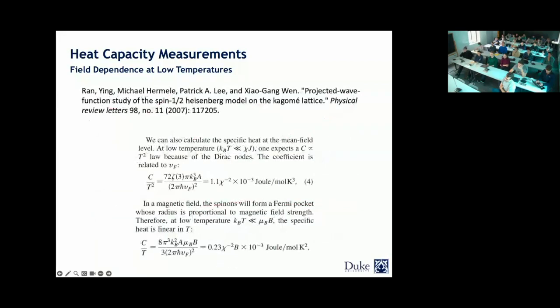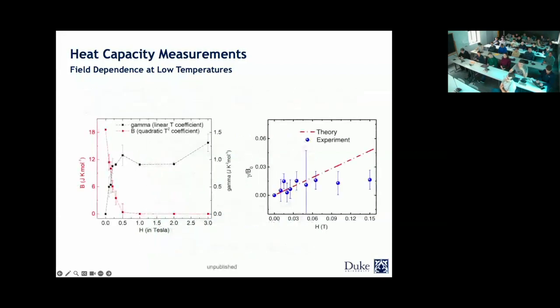Okay, so let me bring you back again in here. The reason for that is that not only would you be able to look at the behavior of the specific heat at two different ranges, zero field and finite field, but if you take the ratio of these two, it actually gives us the value that you would expect to see for different fields. So we did that. We started to look at the different values for gamma and B. The gamma would be the linear T coefficient, and B would be the quadratic coefficient. Looking at this data, you can see that it starts to deviate at basically above 0.3 Tesla, and this is the crossover between them.